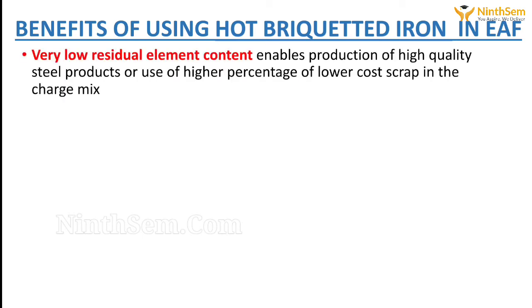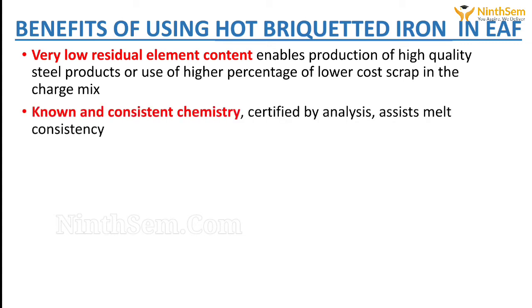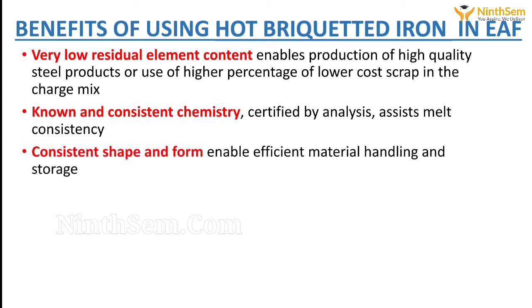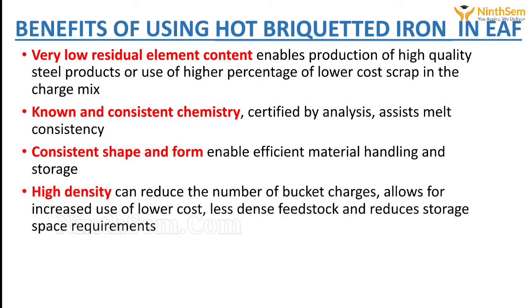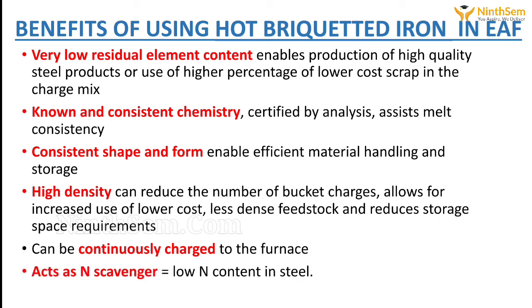Let's discuss. Low residual element content enables production of high quality steel products and use of a higher percentage of lower cost scrap in the charge mix. The chemistry is known and consistent, certified by the quality control department by analysis, and assists melt consistency. Consistent shape and form enable efficient material handling and storage. It has high density, can reduce the number of bucket charges, allows for increased use of lower cost, less dense feedstock, and reduces storage space requirements. It can be continuously charged to the furnace. It acts as a nitrogen scavenger and gives low nitrogen content in the steel.